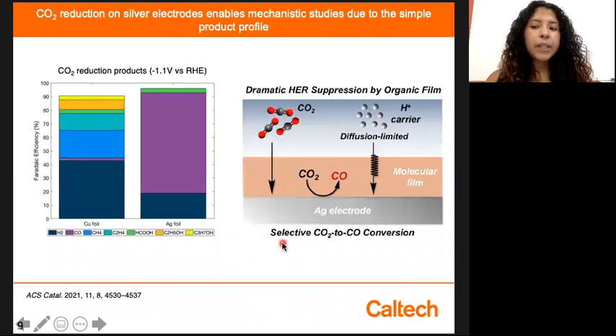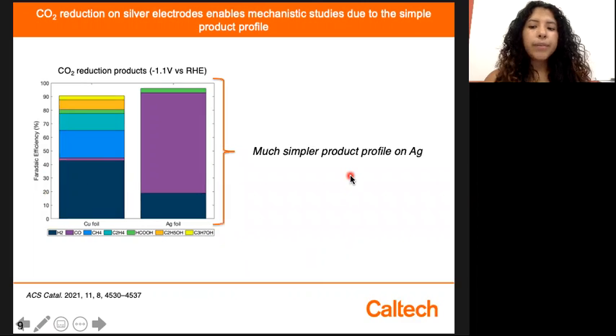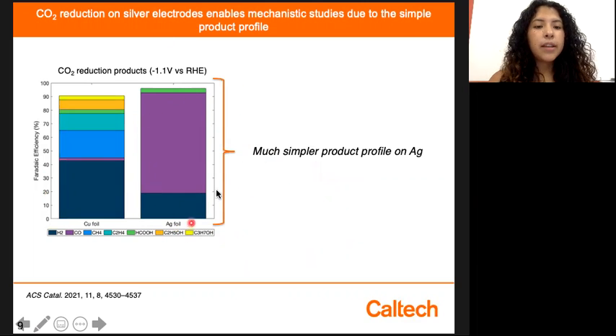And a recent paper that this group has published is the silver paper, in which they were able to study the mechanisms of the additive film on a silver electrode during CO2 reduction. The reason why they use silver instead of copper is that silver has a much simpler product profile, since it can only really make CO, hydrogen, and formic acid, so it is easier to study the intrinsic and mechanistic activity that is happening due to the film. If you take a look at copper-mediated CO2 reduction, you can see that there's a bunch of products, making the whole study of it more complex.